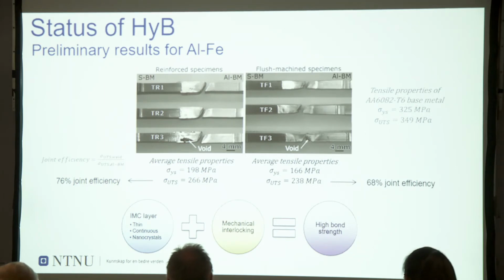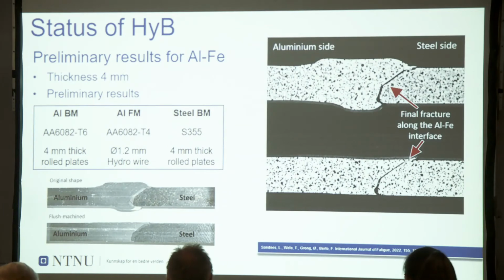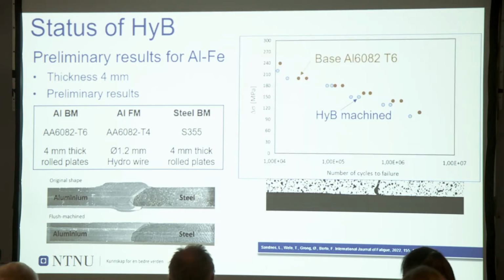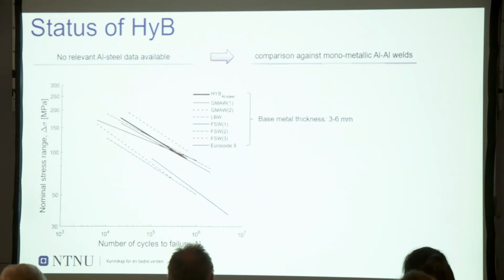The intermetallic layer plus the mechanical interlocking, which I will explain later, is giving the HyB strength of these joints. Dealing with the fatigue results, the failure was happening at the weld toe for the as-welded components, and when we removed the excess metal of the weldments, the failure was still happening at the interface. But again, if you look at the base material with respect to the HyB, we have almost the same fatigue behavior. This means that having the bonding or not having the bonding is not really affecting the component, at least for this thickness.